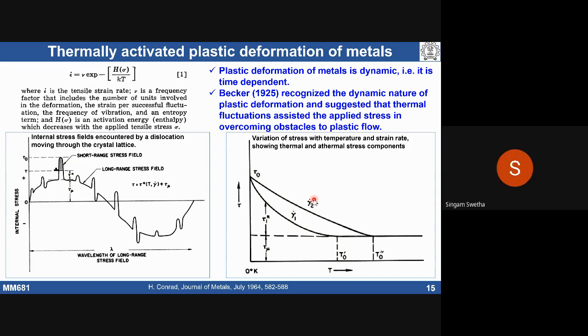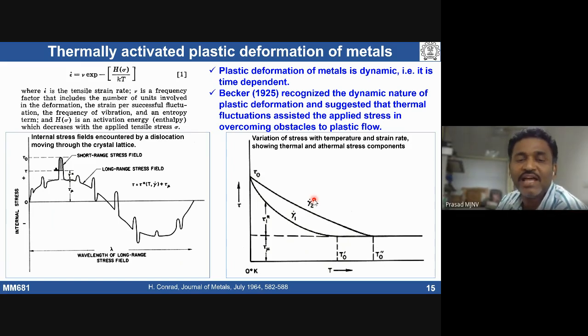Sir, at 0 Kelvin, why do we need to apply maximum stress? Because there is no thermal activation. That means I need to apply, for example, at 0 Kelvin, assume that this is the stress field I have in the material. These are long range stress fields, and these are short range stress fields. These are maximum. This is the biggest barrier. Look at the biggest barrier. So I need to apply it or not, because there is no thermal activation.